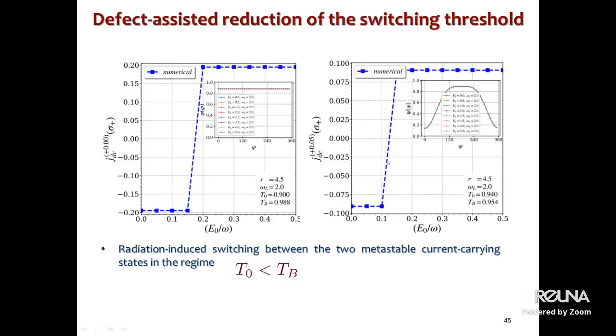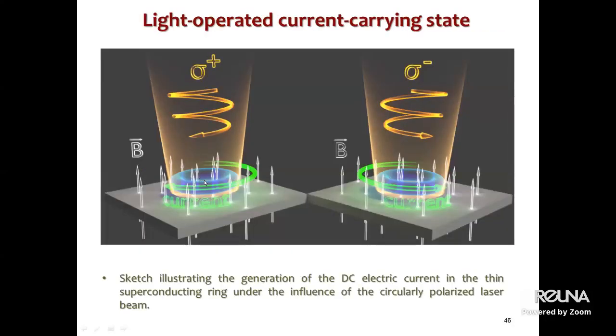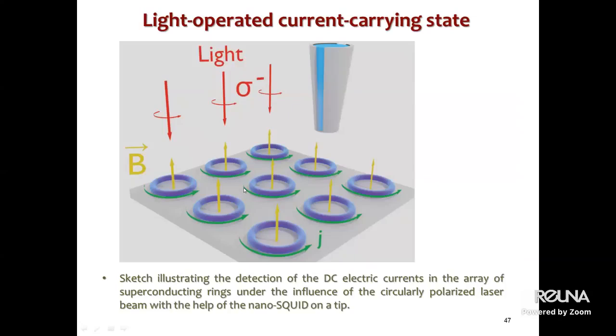And now I'm coming to the conclusions. Here I simply show again that the inverse Faraday effect offers the ability to deterministically optically switch between different current carrying states in superconducting nanorings. That was the model. In reality, one can use a system of rings. A suitable system for observing the predicted effect can be an array of small superconducting rings in a magnetic field that creates half flux quantum through the ring. And then one can use a nanoSQUID to determine the direction of the current.